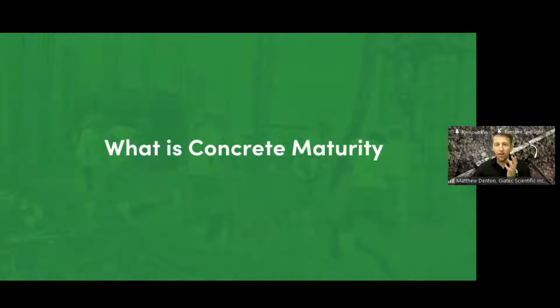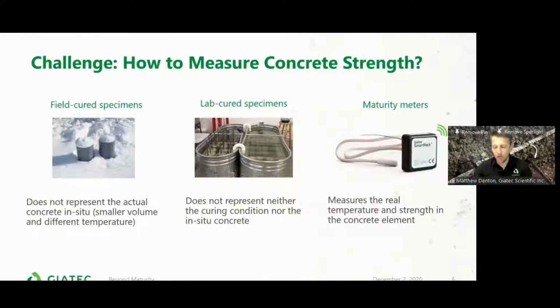So if we jump into the first topic quickly, what is concrete maturity? Concrete maturity is another method that we can use to measure concrete strength. At the moment, there are three main methods out there in the market for us to monitor concrete strength. Either we can do field cured samples or specimens, whether it's a cylinder or a cube in your market, which can obviously change from market to market. We take that sample and keep it on site to try and replicate site conditions for that element, and we would then cure that in similar conditions to what is happening on site.